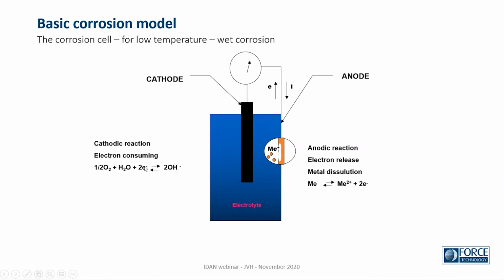And the electron consuming part is oxygen, or it could be hydrogen. So we need to have this process, what we call the cathodic reaction, to have the dissolution of metals in the anodic reaction go on. And if we don't have these two processes in the same environment, same electrolyte, then it doesn't go on. And if we cut the lead between the two, then it will also stop.